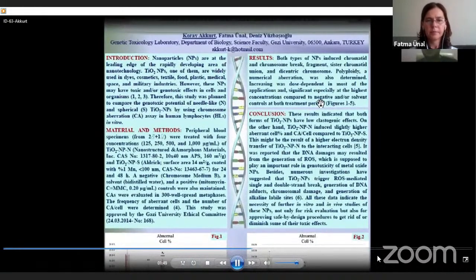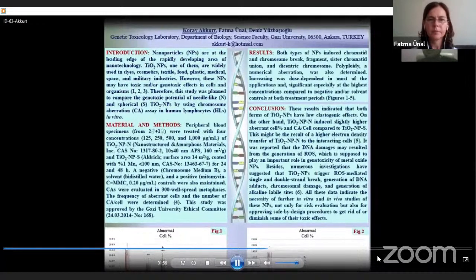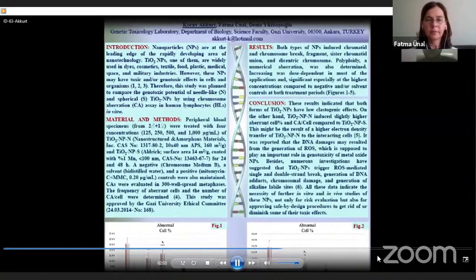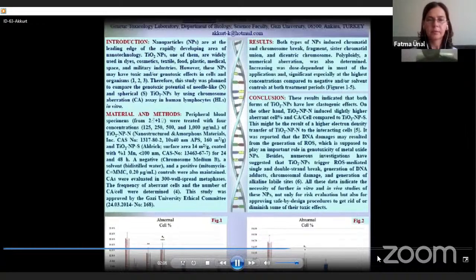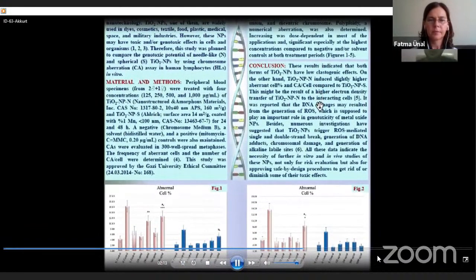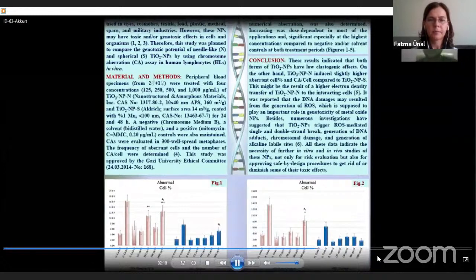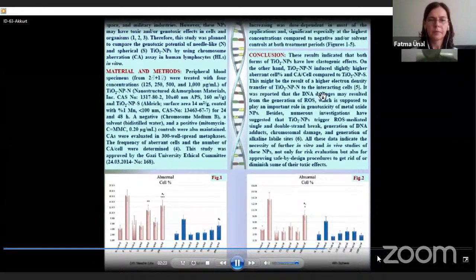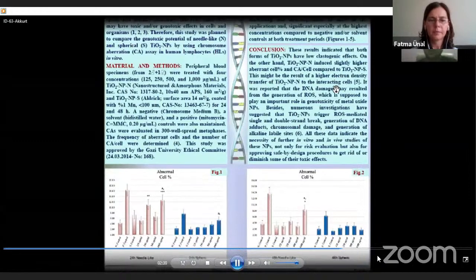When we see the results, both types of nanoparticles induced chromatid and chromosome breaks, fragments, sister chromatid union, and dicentric chromosomes. Polyploidy, which is a numerical aberration, was also determined, increasing dose-dependently in most of the applications and significant especially at the highest concentrations compared to negative and/or solvent controls at both treatment periods. As a conclusion, these results indicate that both forms of titanium dioxide nanoparticles have low clastogenic effects. On the other hand, needle-like induced slightly higher aberrant cells and chromosomal aberrations per cell compared to the spherical form. This might be the result of a higher electron density transfer of needle-like to the interacting cells.